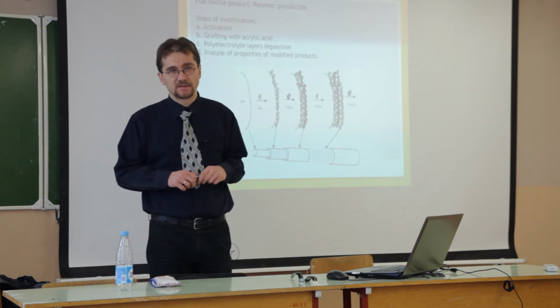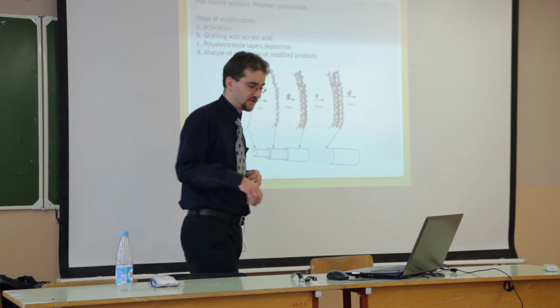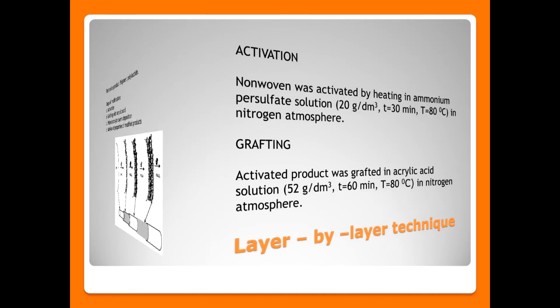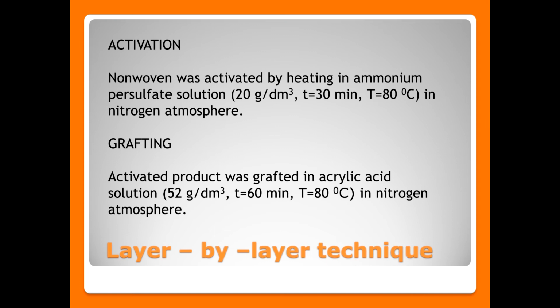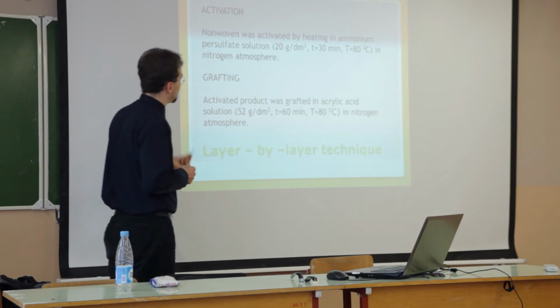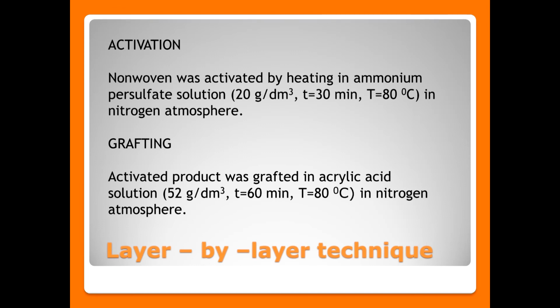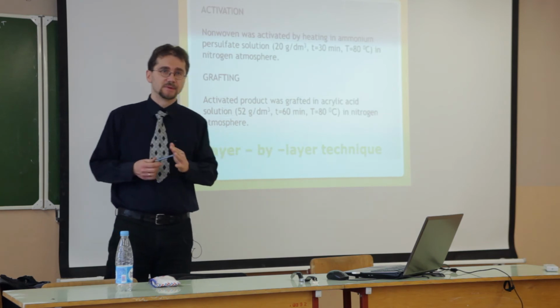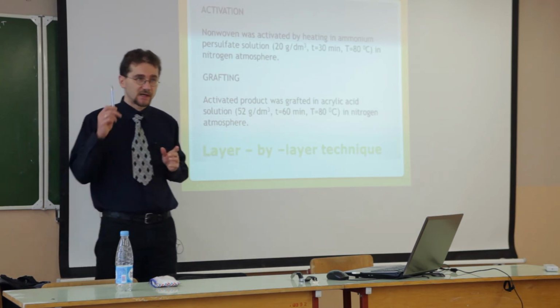5, maybe 6. I received here 4 layers. So again, the activation and grafting, 80 degrees here, 80 degrees here, strong concentrations, 20 grams per liter, 52 grams per liter. So it is not a nice process, but it's necessary. Maybe we will find some method, but I will tell you about that later.